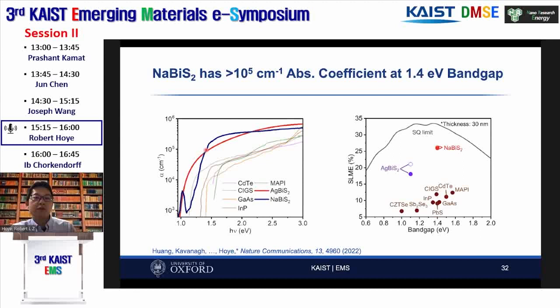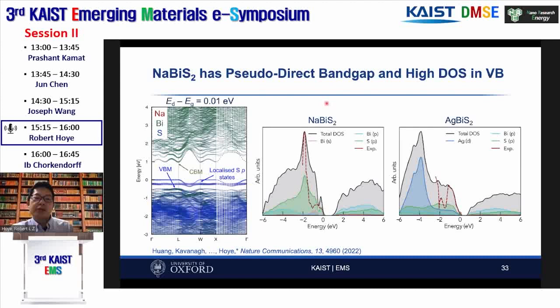And what this means is that with just 30 nanometers of this material, you could, in principle, achieve an efficiency of up to 26% in the fully optimized device. So this means that you could potentially achieve efficiencies comparable with silicon, but using 10,000 times less material. And that's especially important if you want to consider space applications, for example, space photovoltaics for satellites. So we want to understand why the absorption coefficients are so high in this material and what we can learn and apply towards other materials.